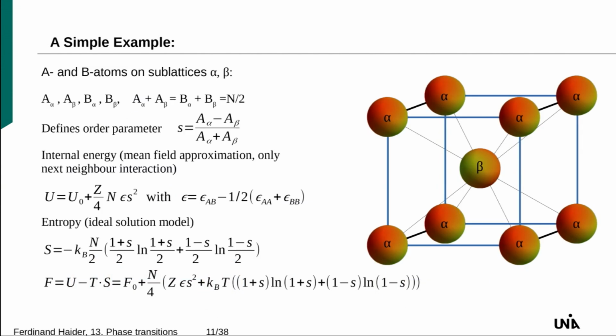How can we describe it? How can we define an order parameter? We can take the number of A atoms or B atoms sitting on the corner sites and on the body-centered sites. I call it A alpha, A beta, and similarly B alpha, B beta. If we are at 50%, A alpha plus A beta is half of the total number of atoms, same for B. Then we can define an order parameter as a difference in occupation of the alpha sublattice and these sites, divided by the sum of those.